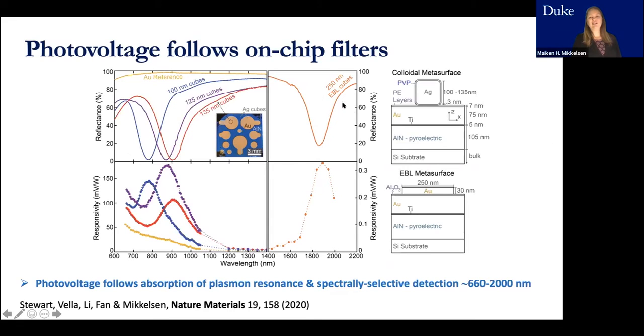And in this case, we also did a test where we fabricated cubes with electron beam lithography that were much larger, 250 nanometers. And what we are seeing is that the photo response, photovoltage or responsivity here, is following these spectral filters very well. So we can see the blue here is corresponding to the blue, the purple to the purple, and the red to the red. So we can see we can indeed get a photovoltage that follows the absorption of the plasmon resonance. And we can create spectrally selective detection from 660 out to 2000 nanometers.